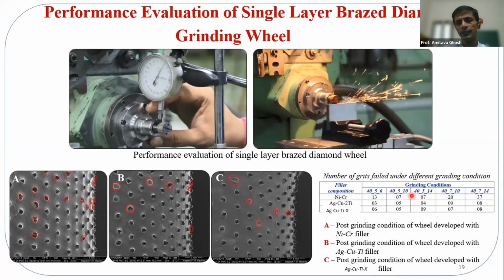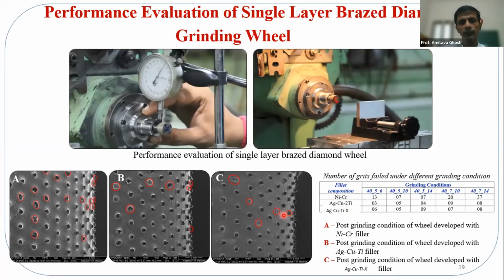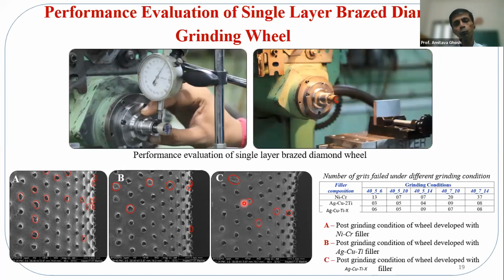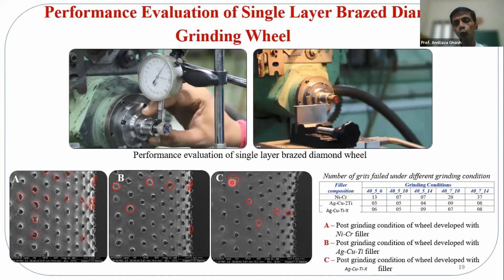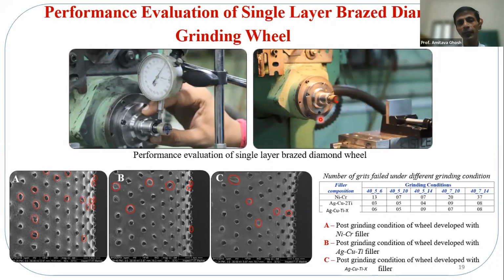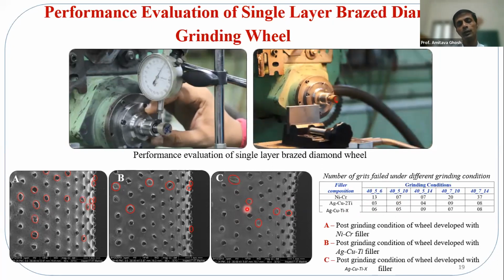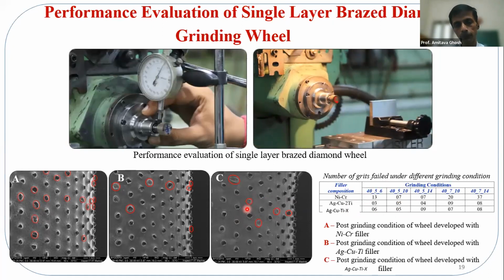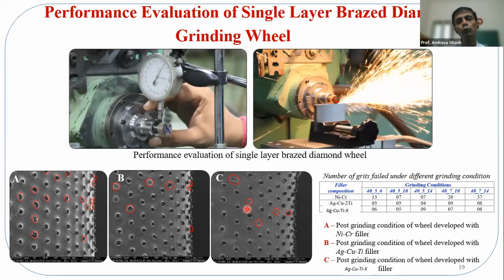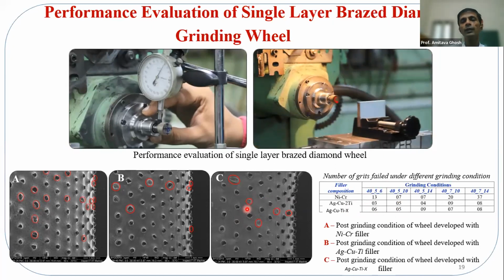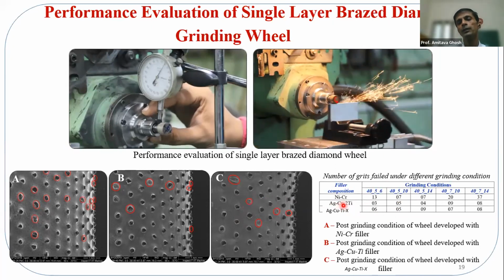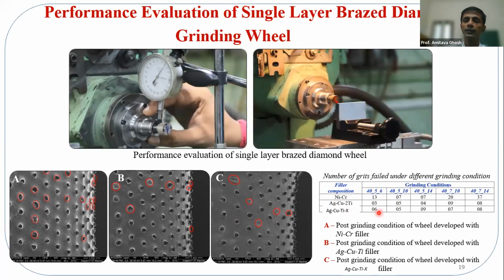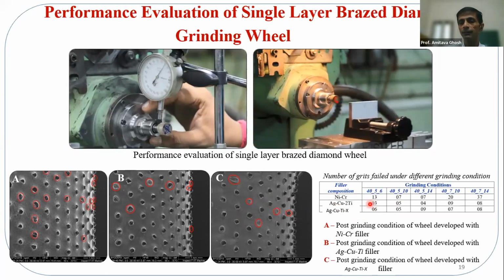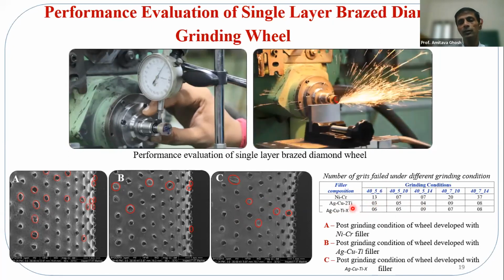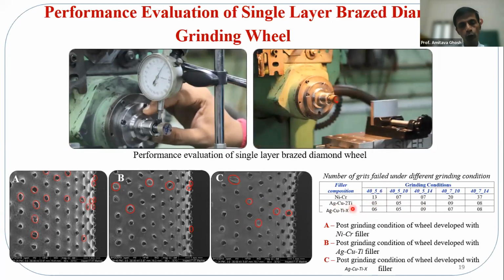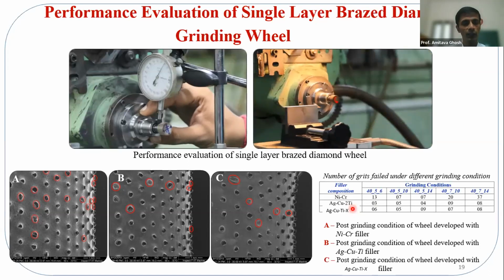So we can see the results, how many grits are getting broken here. The grits never get pulled out because pulling of the grits takes place when there is a weak interface. But grit breakage takes place because of defects inside the grit, and of course the process residual stress. But when we use silver copper based alloys, we can reduce this kind of failure to a greater extent. We use the ceramic matrix, a similar order of failure can be maintained, but we get a bond which is much more durable in nature.